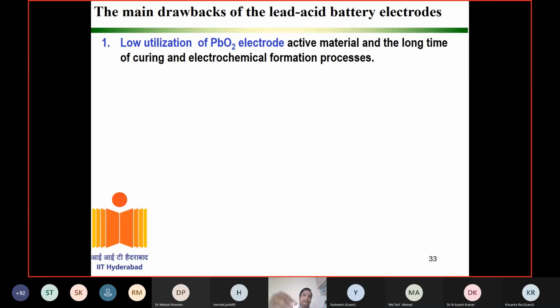I hope many of you may know this. The main issue in the lead acid cell is that the materials are not utilized for the electrochemical reaction. The efficiency is 40-50%, basically. And it takes a minimum of 3 charge-discharge cycles to get full capacity. Initially, if it is a 1 ampere hour cell, you pass 0.1 amp and it's supposed to finish in 10 hours, but a lead acid battery's first cycle itself will take 48 hours.